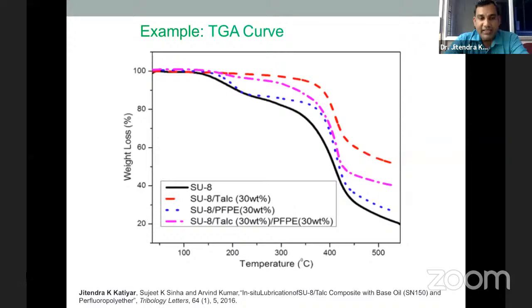So when we add a filler, either solid filler or liquid filler, in the SU8, what is the improvement in thermal stability? Here you can see the degradation in two steps. Up to 100 degrees centigrade, any coating can lose water molecules, whatever moisture is present. After that, you see a further decrease, because of the epoxy element. This is the first decrement, and another second decrement happens here.